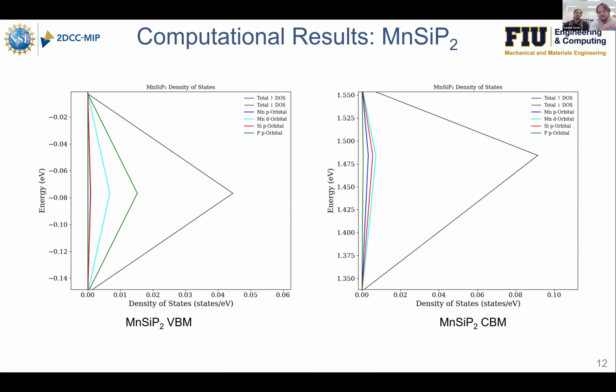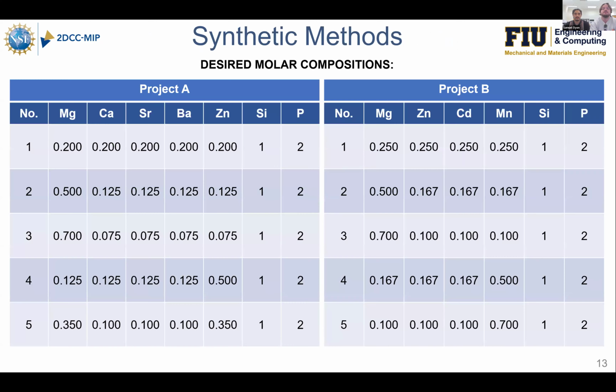And then on the right, the conduction band, some contributions from everything, but this time the major contributor is the manganese d orbital, with also some slight contributions from silicon p orbital, manganese p orbital, and also phosphorus p orbital.